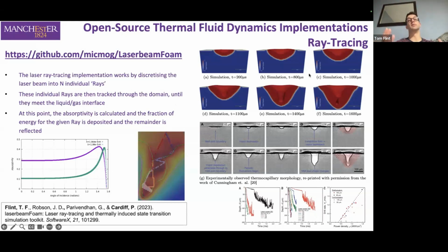So we discretize the laser beam. This is really specific for laser welding applications, and it's important to have that ray tracing capability because of what these plots down here show, experimentally observed plots of penetration versus time. What happens in laser joining applications is that the surface of the weld pool deforms into essentially a parabola, and once that happens you get a very rapid increase in the penetration rate, because all the laser is basically focused onto a much smaller point in the center. So you get this sudden massive increase in the penetration rate, and you don't get that if you don't have the ray tracing capability.